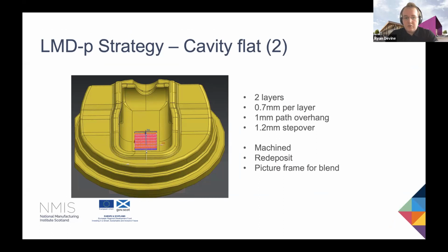However, this area also still had some technical challenges with it, in that we had to ensure a really smooth transition between the H13 die and the MetcoClad 21 areas. So the way we achieved this was we did our initial deposit on, we then machined that flat and then ran an additional bead around the outside of the area. And this has essentially created a sort of picture frame effect. We would then machine this flat again, and this gave a much smoother transition and blend between the 2 materials.